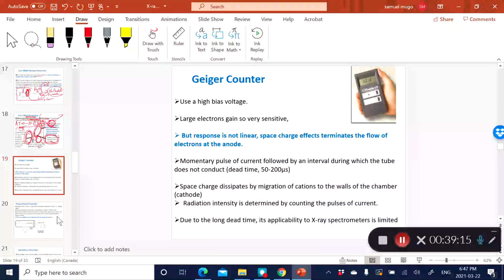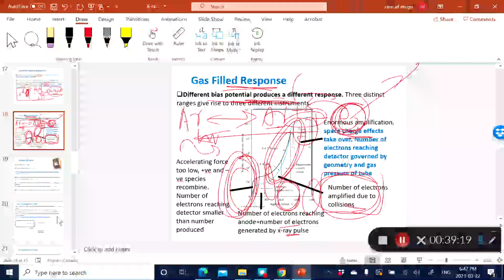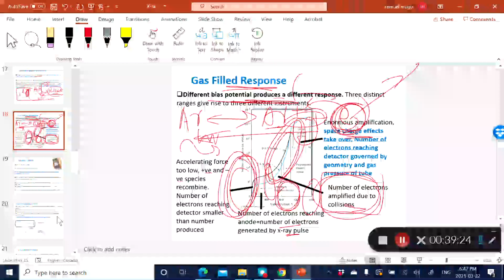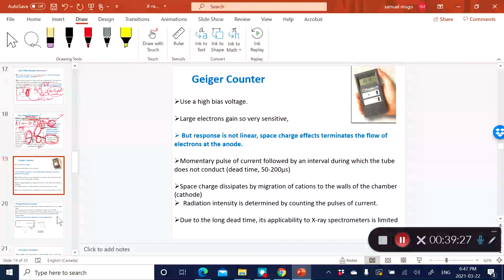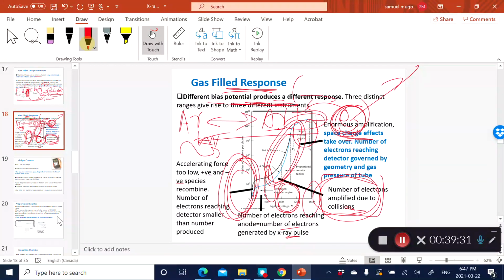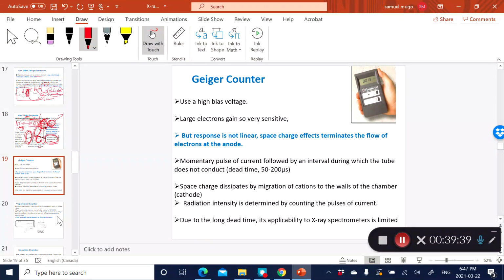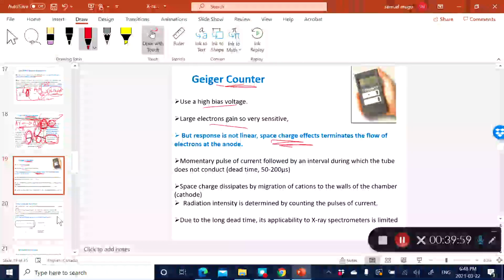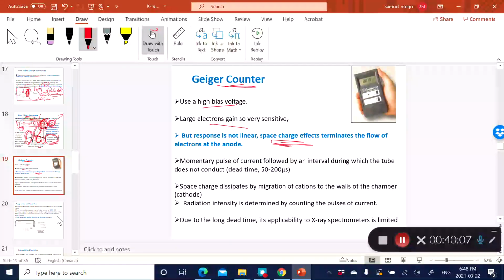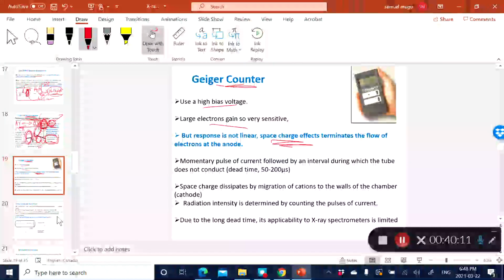And so based on those different scenarios, you can actually make different types of X-ray detectors. For example, if you use very high voltage, as I said up here, then you can make what you refer to as the Geiger counter. So you're using a very high bias voltage. So a very large number of electrons is generated, meaning the detector is very, very sensitive. However, you get the so-called space charge effect, meaning it tends to be pulsated. All right, meaning you don't get a continuum beam of signal because of this space charge effect taking place.